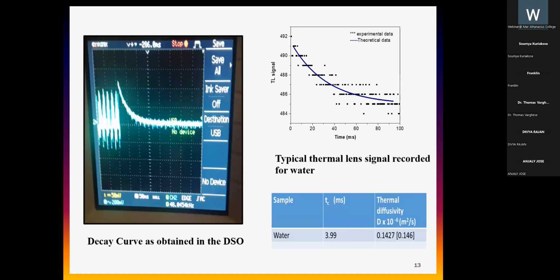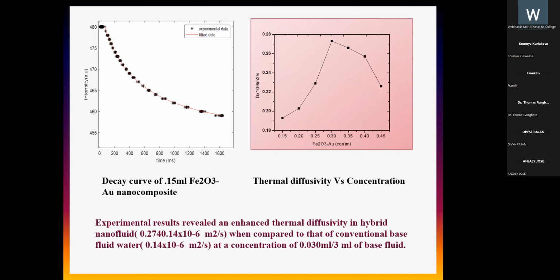thermal diffusivity of the nanofluid. Here, the first figure shows the decay curve of 0.15 ml of nanofluid from the intensity versus time graph. And the second graph is the thermal diffusivity versus concentration graph of nanocomposite at various concentrations per 3 ml of base fluid.